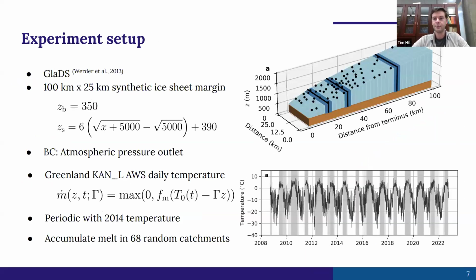To actually test what this does to the model drainage system, we implement this in the glacier drainage system model. I use a synthetic ice sheet margin setup, intending to represent part of the land-terminating Greenland ice sheet. We force it with air temperatures from the lower K-transect weather station, hoping that we get the right temporal variability of surface melt, because that's really important for driving subglacial drainage development and variations. I have 68 moulins on the surface and accumulate melt within those to provide localized inputs to the bed.